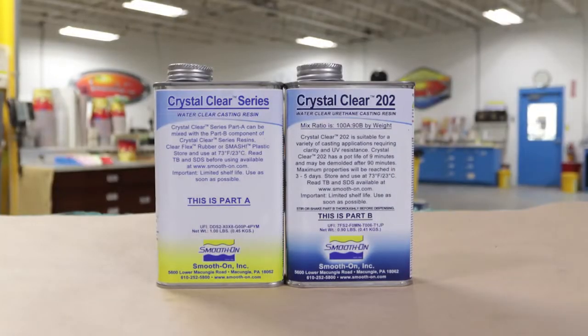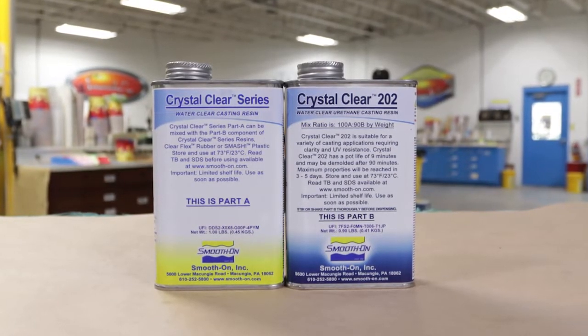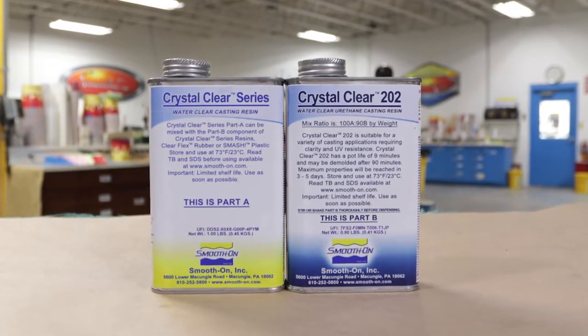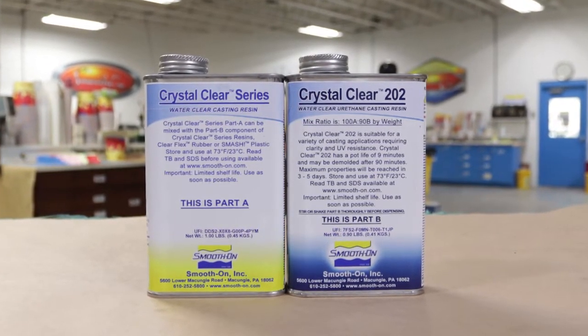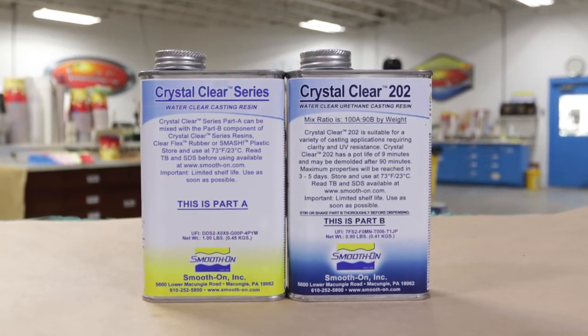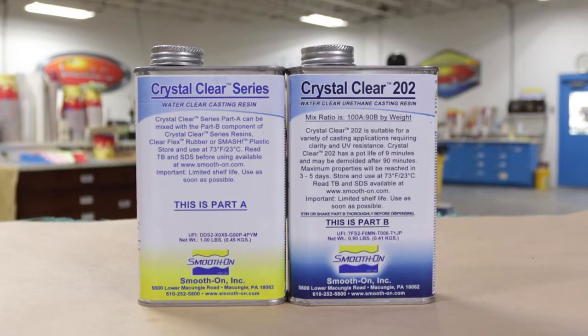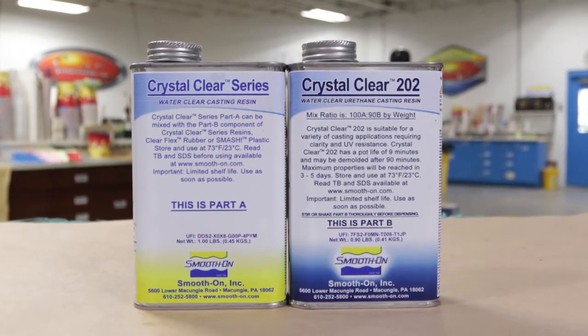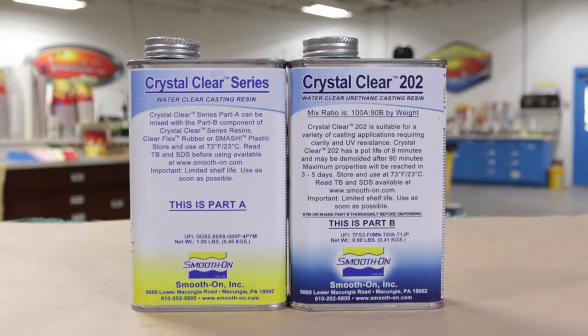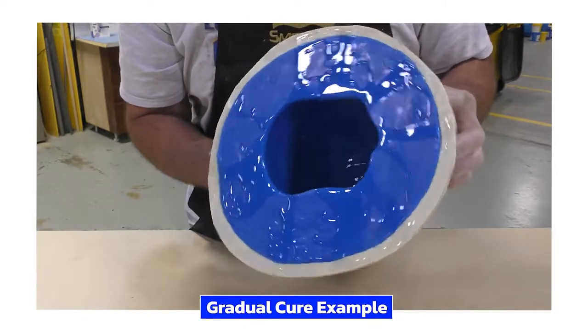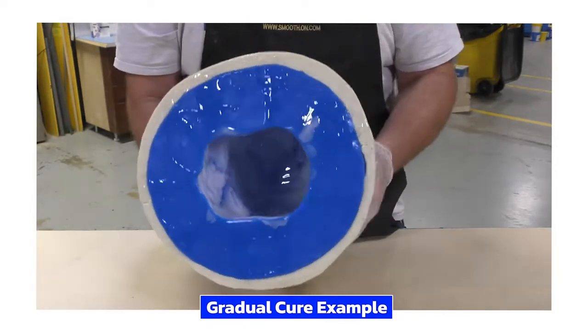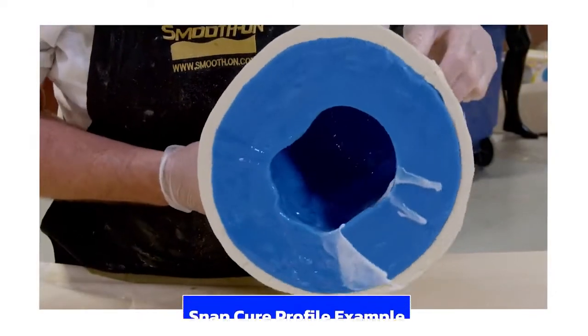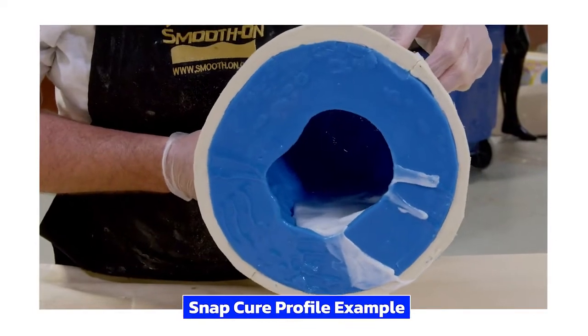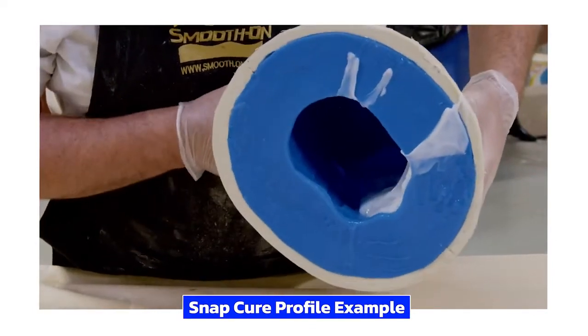The crystal clear is a water clear urethane casting resin that was designed for casting at very specific thicknesses and has what is known as a snap cure. Now, our challenge is to use this product to do a rotational casting, which is not what it was originally intended for. While rotational casting materials have a gradual cure profile that allows us to keep the material inside the mold moving around until it sets up, a snap cure material has a fast cure profile and it goes from a liquid to a solid state in a very short period.